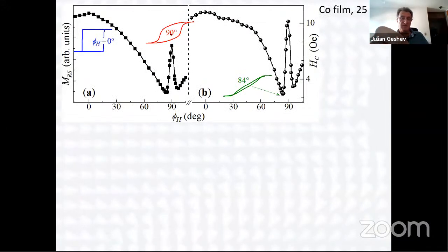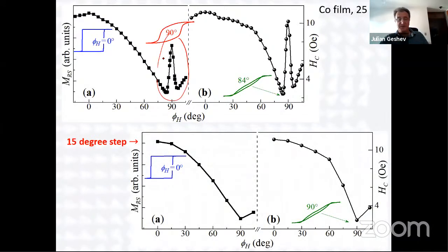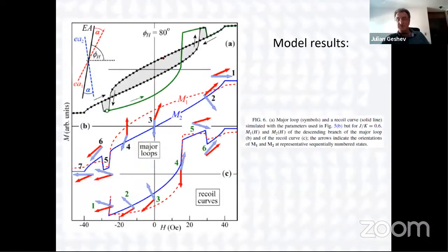This is, for example, a cobalt film of 25 nanometers. You got this collapsed axis. But if you perform the measurement with a 15 degree step in angular variation, you easily can miss this effect. So it's nothing unusual, actually. It's quite common, we believe. Finally, we were able to explain this phenomenon using a simple model of interaction of grains, which is in quite good qualitative agreement with the experiment.